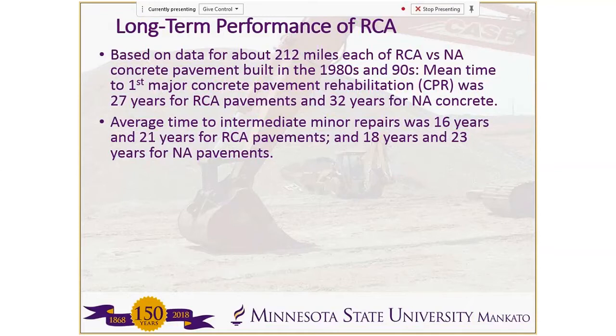For the minor repairs, we found that by the time they get to the major CPR, most commonly they undergo 2 minor repairs along the way. And those times were fairly similar for both of them. So 16 years and 21 years for the RCA pavements, 18 years and 23 years for the natural aggregate pavements.